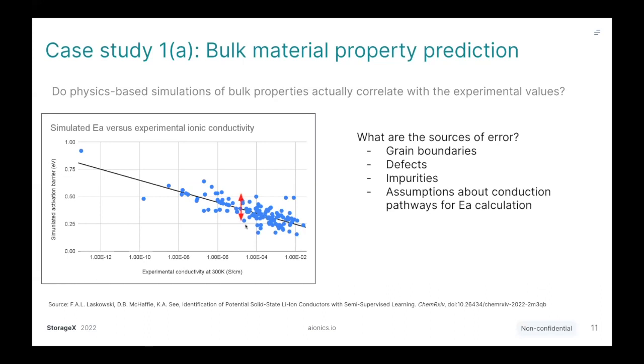Of course, there is some spread in the data, so it's not perfect. There are outliers. And you can ask the question, well, what are the sources of error here? There could be a lot, right? So any computational method that just looks at the crystal structure of the unit cell is not going to take into account anything involving grains and grain boundaries. And we have some forthcoming work looking specifically at the role of grain versus bulk conduction as a predictor for the correlation between a DFT conductivity and experimental conductivity. So that's important. Defects and impurities typically are not going to be modeled unless you explicitly put them into a computational calculation.